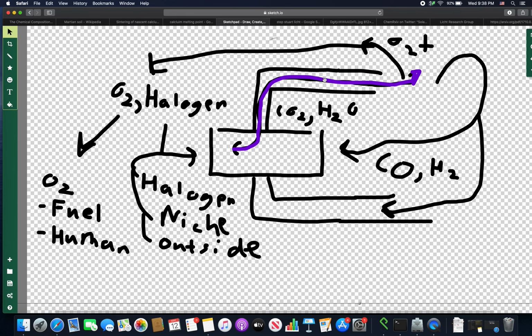And we have the hot oxygen. And also we can recover some of the heat from the oxygen here with heat pumps and stuff, which could cool down the oxygen to a nice temperature and heat everything efficiently. If you use heat pumps to cool down these leftover gases, you recover more heat than you put in to make that. So actually you get more than 100% efficient.